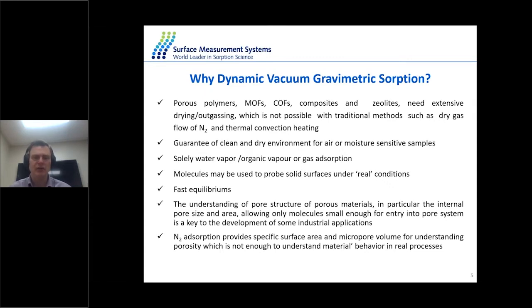Vacuum gravimetric systems also guarantee a clean and dry environment for, let's say, air or moisture sensitive samples. What it means is, if your sample reacts with the air, as some of the MOFs do. So if you work under vacuum, you don't have to worry about side effects, like what might happen to my MOF if it reacts with 400 ppm CO2, which might send it to a different phase. The other big benefit is solely water vapor or organic vapor gas sorption. What it means is we measure the vapor pressure of water under vacuum, and this is measured directly by using the Baratron. So there is no effect of a carrier gas like nitrogen and air on the sorption process.